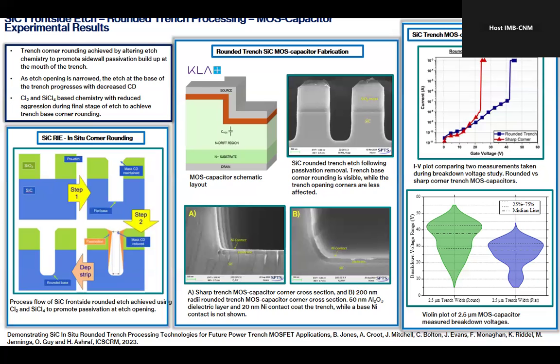So we focused on aluminium oxide. And in fact, our partners at KLA developed this process flow in order to achieve the rounded sidewall. So you can see there's this fancy passivation here. They patented this, and actually the masking and the subsequent passivation step here is quite advanced, so it's not so straightforward from a processing perspective to achieve a rounded etch. There's also chemistry involved, and this silicon tetrachloride chemistry is very important, but it's a combination of the chemistry and the process to create a nice rounded trench etch.